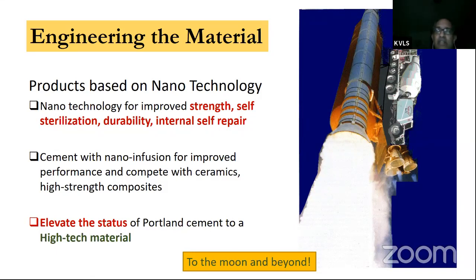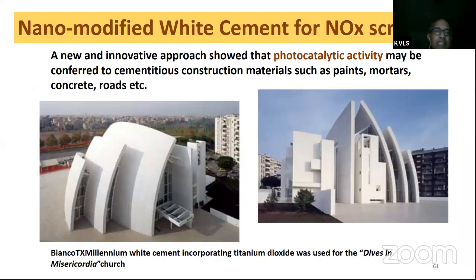And basically we're looking at cement now so that we can produce this material and start competing with ceramics and high strength composites. It's not just limited to use in concrete, essentially elevating the status of Portland cement to a high-tech material. So that's what we, the material scientists who are working in cement and concrete, are now currently working on. And to give you an example, cement which is infused with nano titanium dioxide crystals has already become a reality.